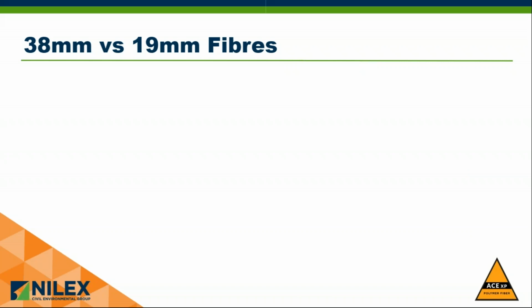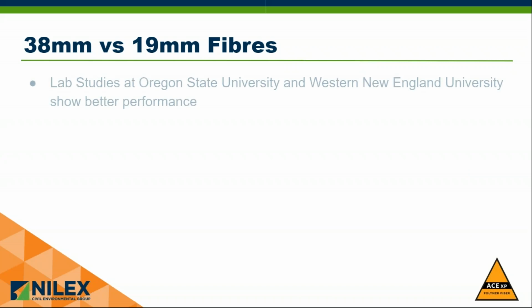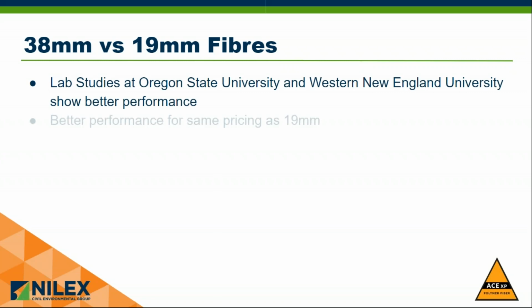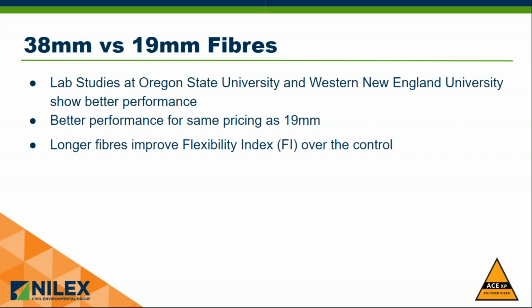So how does the longer fiber perform versus the shorter fiber? So there's a lot of lab work that's been done in the United States. And what we're basically finding is that we get the better performance for the same price. But the flexibility index shows testing it's almost a 37% increase over a control mixture with the longer fiber. So because you're increasing the flexibility index, it's suggesting that the longer fibers improve the cracking resistance of the asphalt pavement.